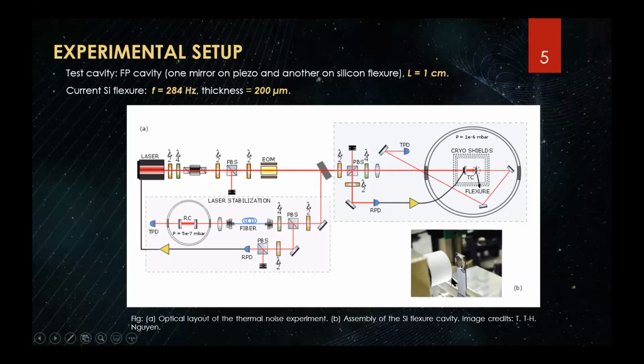As you can see over here, we have an input PZT mirror on which we have a slow feedback loop to counteract cavity length drifts. And then this is our flexure, and this cavity is about just a centimeter long. And I should highlight that the current flexure that we have in our experiment has a resonant frequency of 284 hertz, and the thickness is 200 microns.